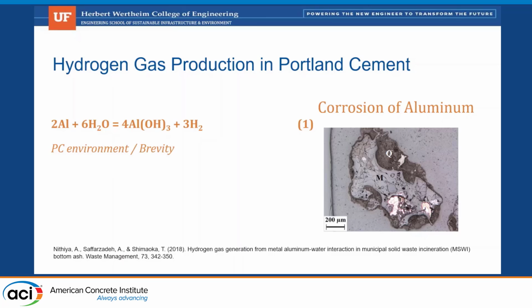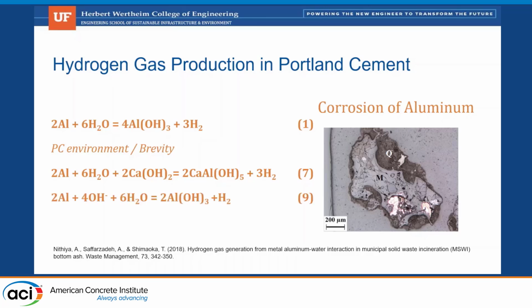When we get into our Portland cement environment, we obviously have elevated pH, we have calcium, and so on. And so skipping a number of equations, we see that we have, again, our metallic aluminum, our aqueous environment, and that turns into a corrosion product and the evolution of hydrogen gas. This is obviously the important part for what we're doing as we use it towards autoclaved aerated concrete. And this is just basically our final equation in that, we'll call it a brief derivation of hydrogen production from